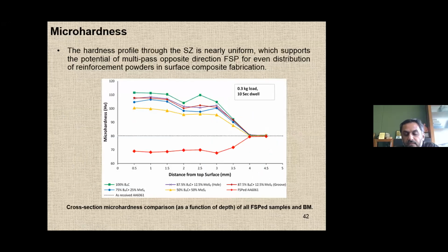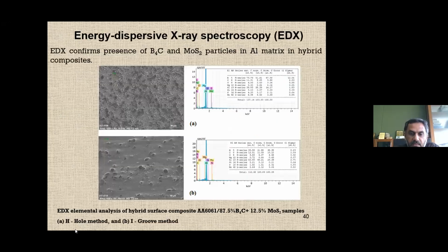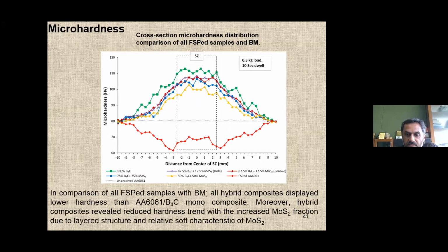So we found that among all the compositions which have been varied, we then did the hardness measurements across the stir regions for all the compositions from 100% B4C, right? And you see, this is your red one, which is your FSPed. And you realize that the 100% B4C has the highest hardness, right? But if you compare with this 12.5% MoS2, which has lower hardness. So that also confirms that all hybrid composites display a lower hardness than the B4C mono composite. Moreover, the hybrid composites reveal a reduction in the trend with the increase in MoS2 fraction. As the MoS2 fraction increases, you see there is a yellow one. You see the yellow one, which has 50%, which has the least, right? So that is how the hardness trend is.